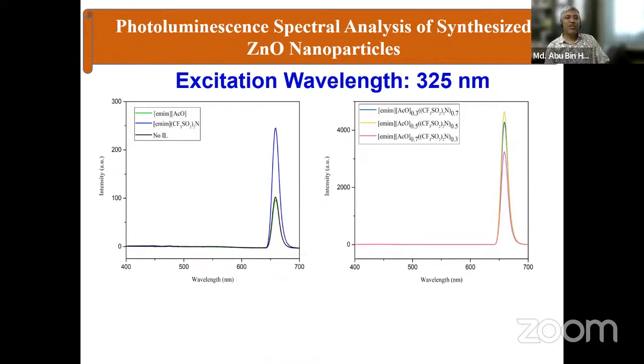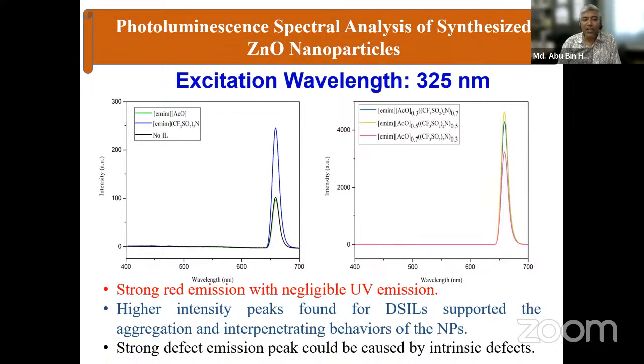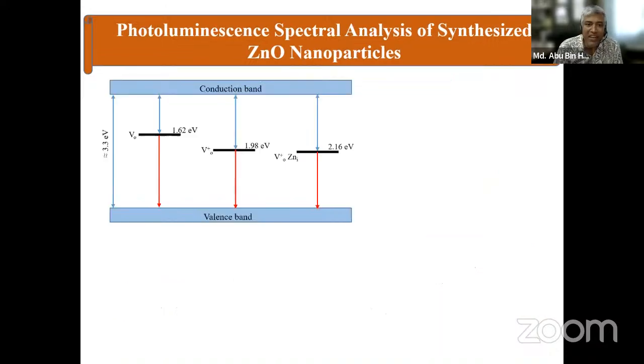Finally, we will show some preliminary results of photoluminescence. Here I have shown the photoluminescence spectral analysis of the synthesized zinc oxide structures. Excitation wavelength was 325 nanometer. And you can see that depending on the structure of the ionic liquids and double salt ionic liquids, strong red emission with negligible UV emission can be observed. Higher intensity peaks found for double salt ionic liquids supported the aggregation and interpenetrating behaviors of the nanoparticles, and the strong defect emission peak could be caused by intrinsic defects.